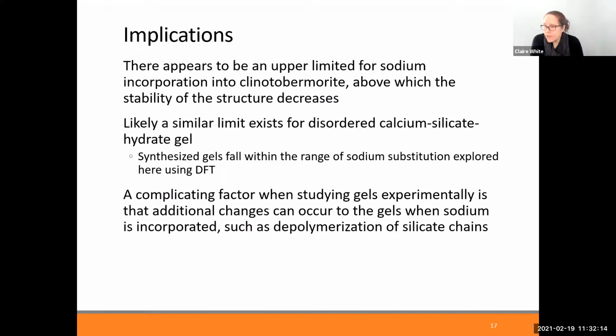So that's for looking at sodium incorporation into these calcium silicate hydrate gels, where we used density functional theory on a model crystalline phase to get that information. There seems to be an upper limit for the amount of sodium that you can incorporate into this model phase, above which there's an energy penalty associated with the structure. It's likely, we can't say 100%, that a similar limit exists for disordered calcium silicate hydrate gels, but that's still to be explored. All that I'm saying here is we looked at the clinotobermorite crystal structure, and that's where we saw the differences.